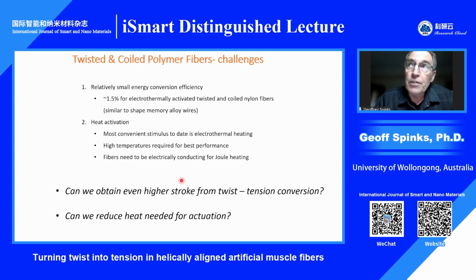And the other aspect that's a challenge is that the best performing twisted and coiled tensile actuators operate at quite high temperatures. So we're using nylons typically with melting temperatures up to about 250 degrees C. And the best performance occurs when they're heated as high as possible without damage or melting. Now, those temperatures are not suitable for lots of applications. So we were interested in trying to produce twisted and coiled tensile actuators that operated at lower temperatures. So I'd like to just pick up on these two dot points down the bottom here.